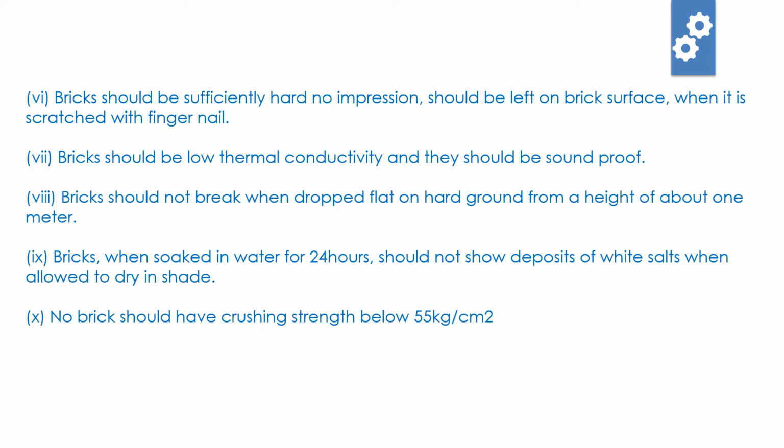Bricks should not break when dropped flat on hard ground from a height of about 1 meter. Bricks, when soaked in water for 24 hours, should not show deposits of white salt when allowed to dry in shade. No brick should have crushing strength below 55 kg per centimeter square. Please remember this is crushing strength.